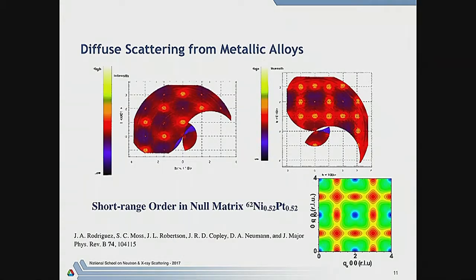Now, here's just a very quick run-through. The very first diffuse scattering modeling was actually done on metallic alloys. And this was a cunning one where, because nickel-62 has a negative scattering length, you can actually make a null alloy. What that means is that the Bragg peaks themselves have zero intensity, which must have made it fun to align. But it meant that all the scattering here is diffuse scattering. And what it's telling you, exactly as in that example earlier, is the tendency for the nickel and the platinum ions to either cluster or anti-cluster. In this case, I think they tend to cluster. And that's important if you want to understand the metallurgical properties of this material.